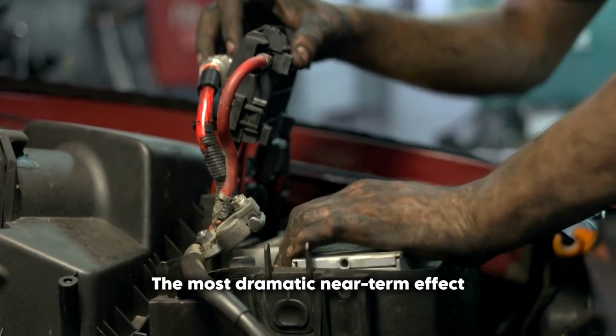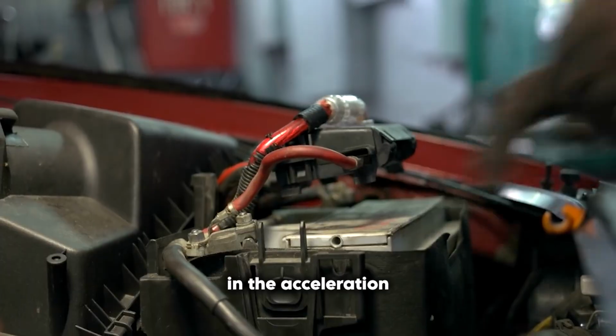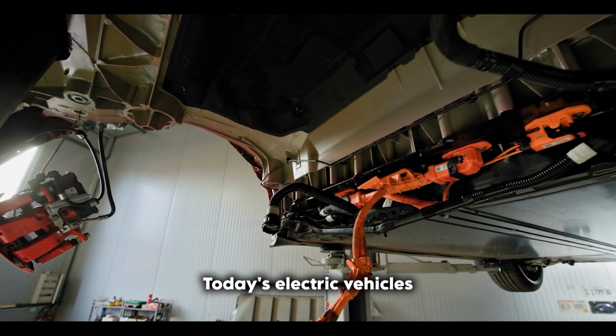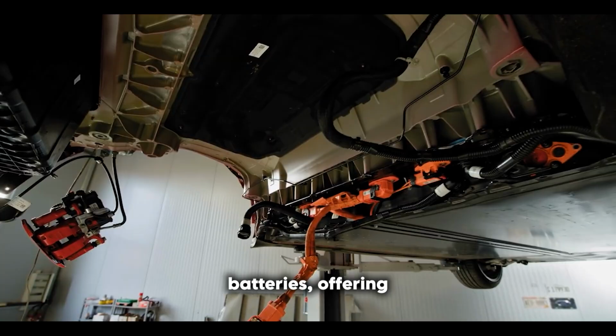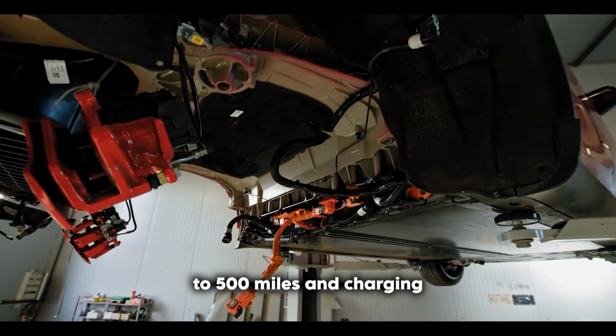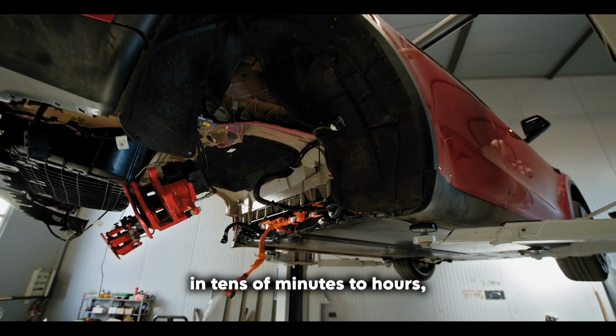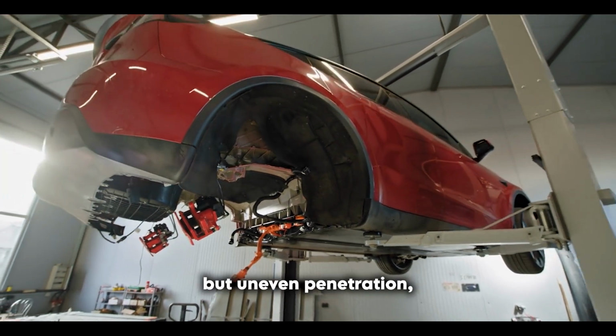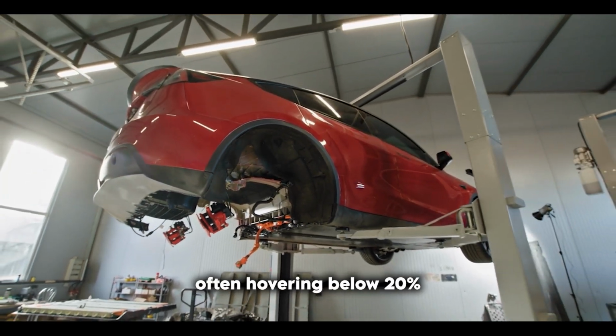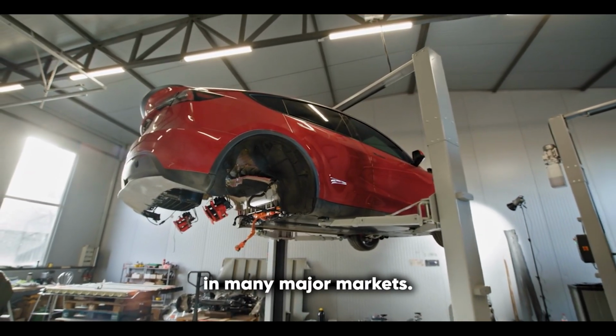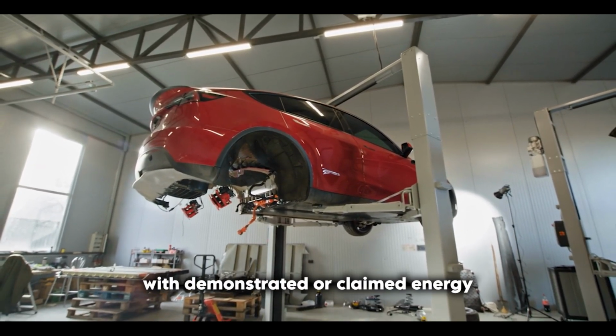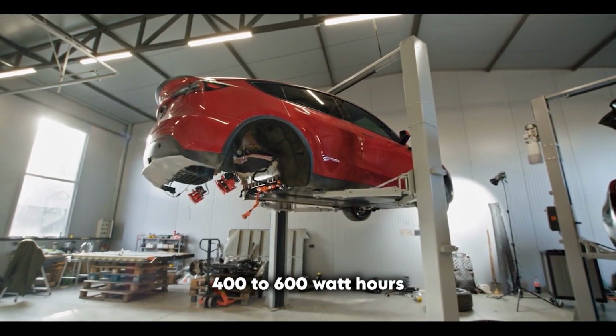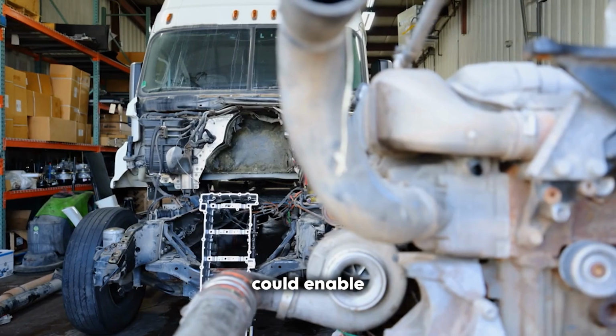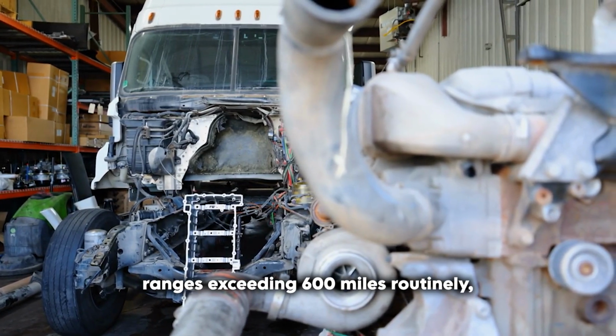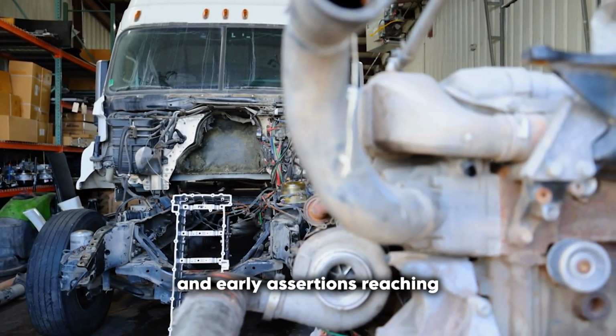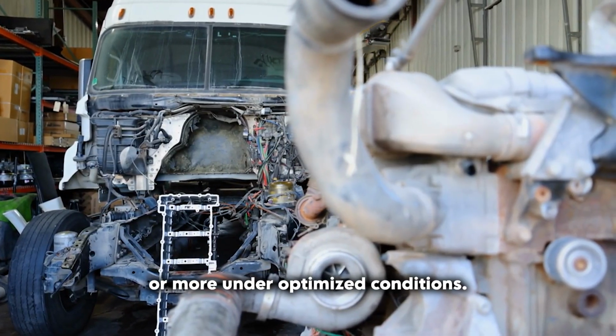The most dramatic near-term effect would likely appear in the acceleration of electric vehicle market share growth. Today's electric vehicles, constrained by lithium-ion batteries offering typical ranges of 300 to 500 miles and charging times measured in tens of minutes to hours, have achieved significant but uneven penetration, often hovering below 20% in many major markets. Solid-state batteries with demonstrated or claimed energy densities approaching 400 to 600 watt-hours per kilogram could enable ranges exceeding 600 miles routinely, with some projections and early assertions reaching 1,000 miles or more under optimized conditions.